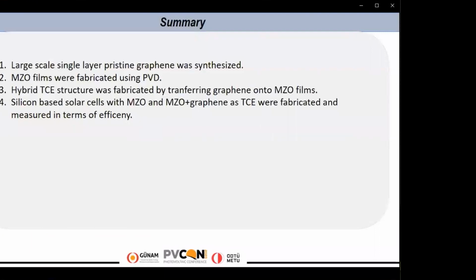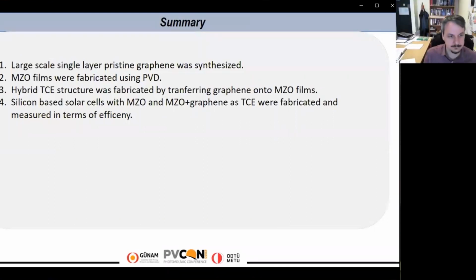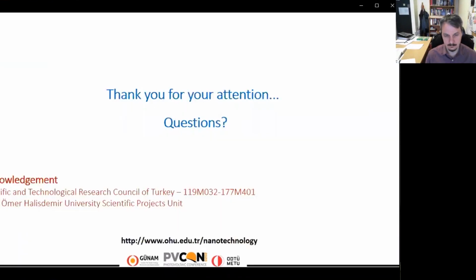Large-scale, single-layer pristine graphene was synthesized. Molybdenum doped zinc oxide films were fabricated using PVD. Hybrid TCE structure was fabricated by transferring graphene onto MZO films. Silicon-based solar cells with MZO and MZO graphene TCE were fabricated and measured in terms of efficiency.